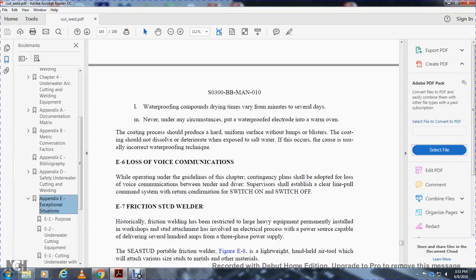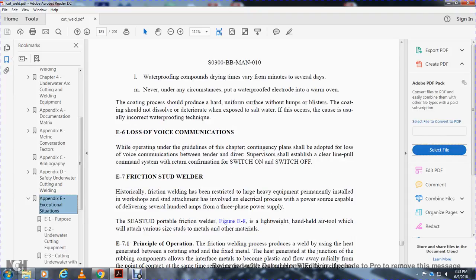Alright, waterproofing compounds' dry time varies from several minutes to several days. Never under any circumstances put waterproofed electrodes in a warm oven. The coating process should produce a hard and uniform surface without lumps and blisters. The coating should not dissolve or deteriorate when exposed to salt water. If this occurs, the cause is usually an incorrect waterproofing technique.